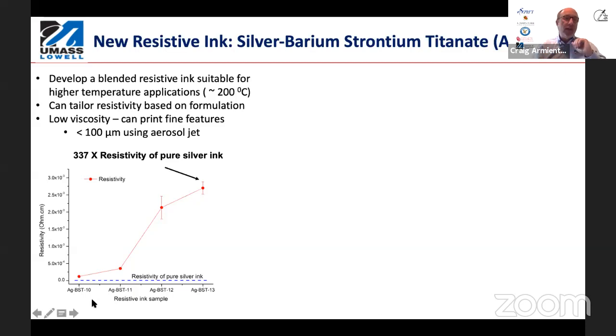And what you see here is a plot of resistivity for different formulations, AG, BST, 10, 11, and so on. We can get a resistivity about 337 times the resistivity of pure silver ink. Now, in the context of doing this, we can print this with a fine line on an aerosol jet because it's basically a conductive ink with particles in it. And that's worked out quite well.